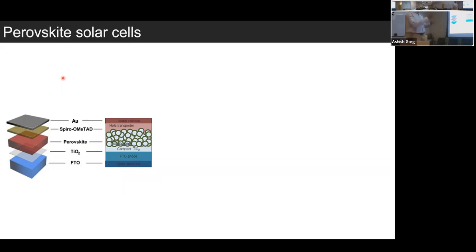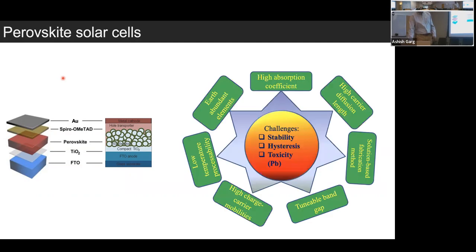Earlier it was impregnated with a variety of materials, but modern architectures simply use a thin layer of perovskite without impregnating it with anything else. The good things about perovskite are that it has a high absorption coefficient, it has a high diffusion length, you can solution process the devices, it has a tunable band gap, and it uses cheap elements which are abundant in nature.